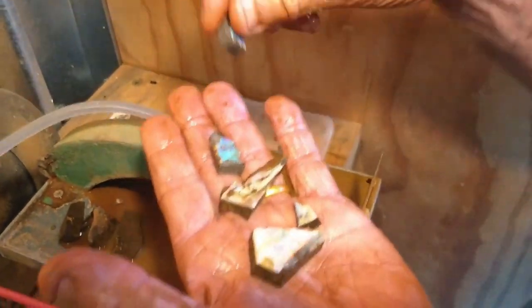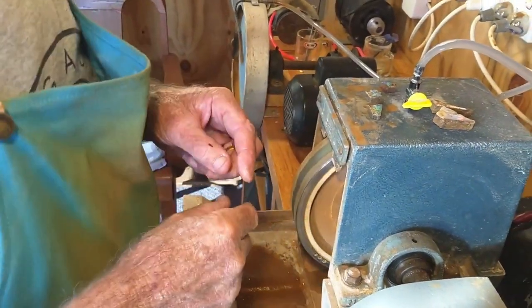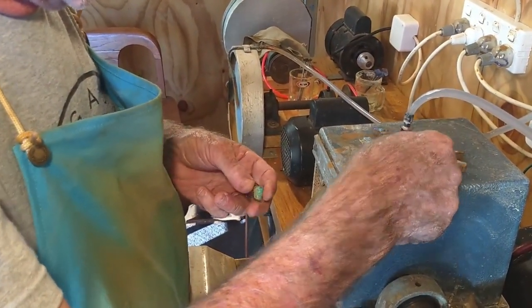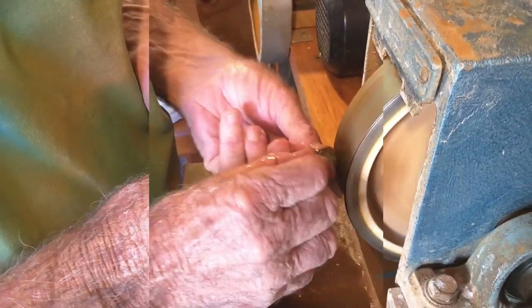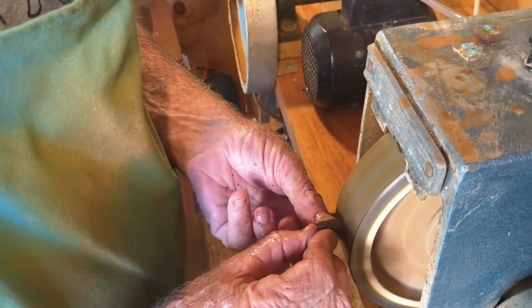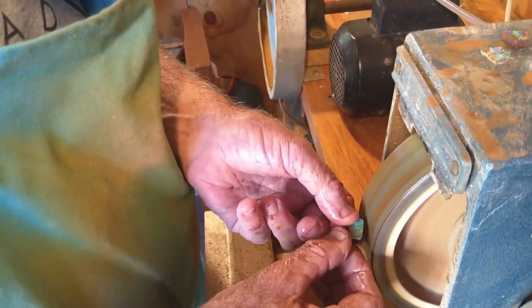Let's pull them all up and see what we've got — okay, we've done the preliminary cuts and started a little collection. Starting on the coarse grinder to knock the material off — it's going to be a bit noisy. Using diamond-plated wheels, he'll just take off a little bit of iron to get down to the color. All stones need the corners rounded — opal with sharp corners has too much chance of chipping or breaking the stone, so he takes a little corner off as well.